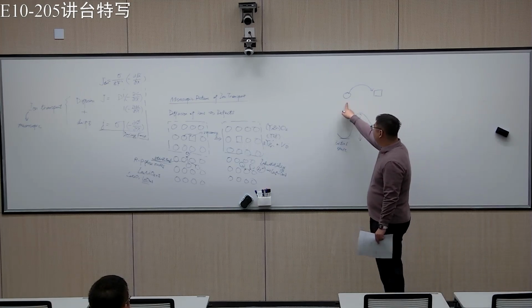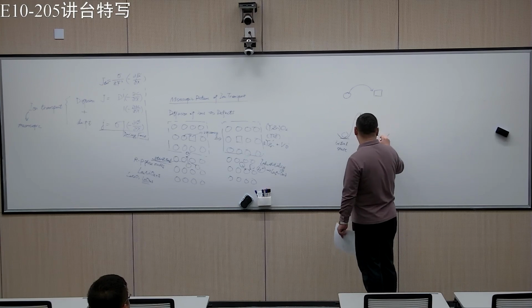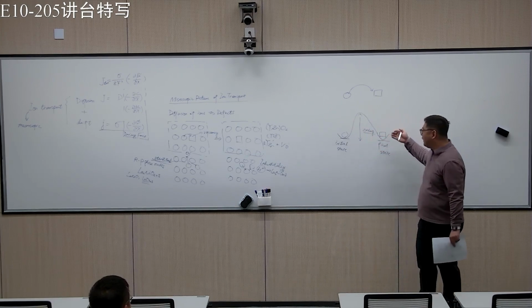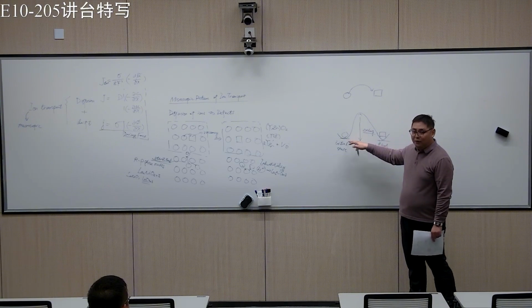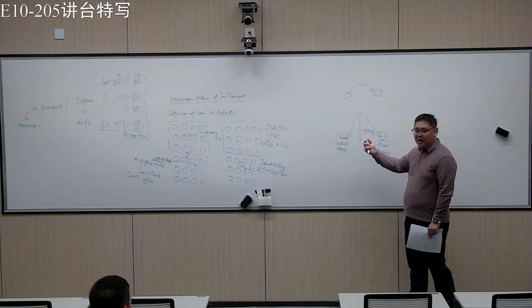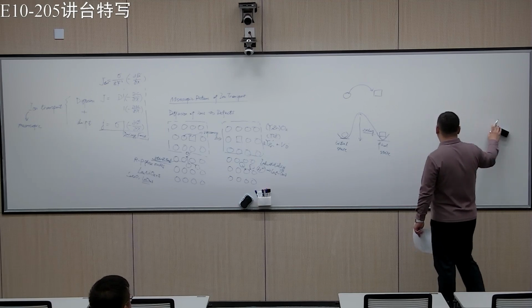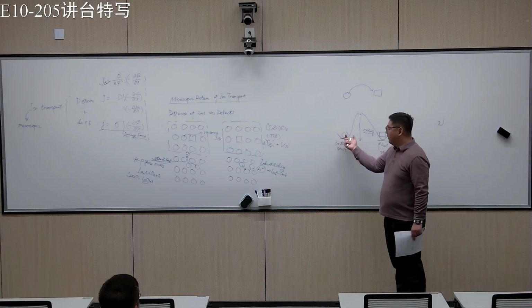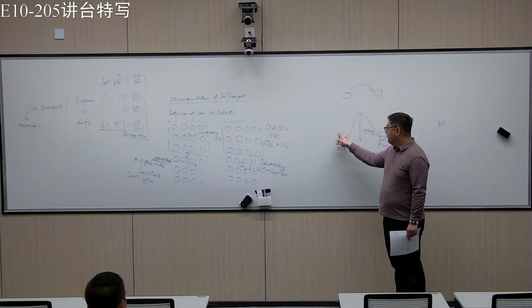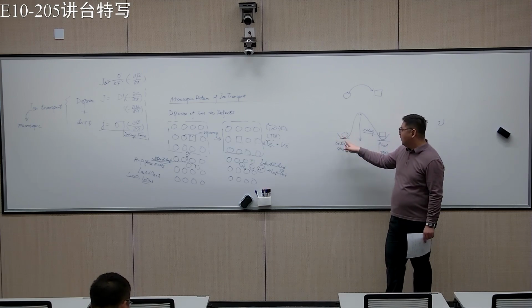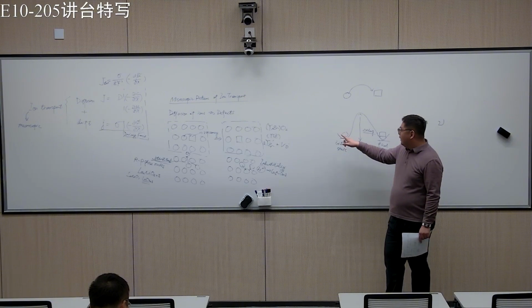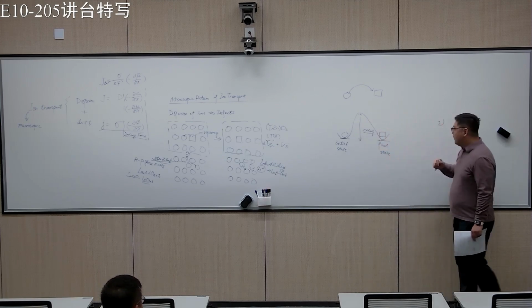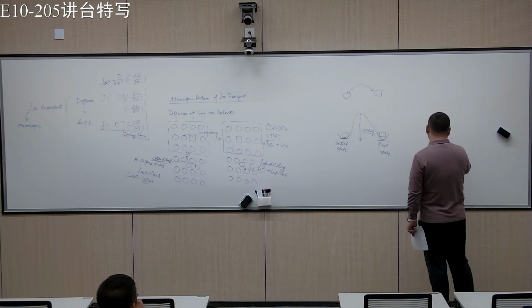So the picture is if you have an ion here, okay, and a vacancy here, there will be some kind of lattice vibration. The lattice vibration basically keeps the ion near this initial state, right? Then it will attempt to jump to the other side, overcome the barrier. Okay. So usually what we use is something called nu. This is basically the attempt frequency.